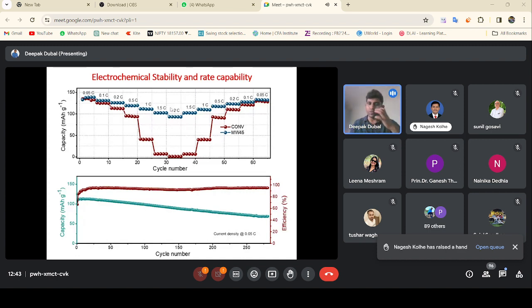So why this happens is our hypothesis, we are still exploring the mechanism of the microwave synthesis process, but our hypothesis is that when we apply the microwaves, or when we start the furnace, it brings the temperature, like a synthesis temperature for crystal formation, very rapidly. So the sample doesn't get extra heat. And that is the reason the material we are getting through this microwave process is very pure, defect-free, and has very few impurities. That is our hypothesis.